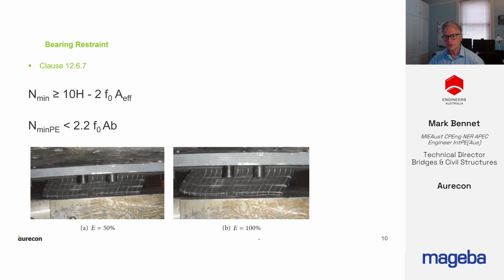When a bearing is subject to shear deflection, the bottom rear corner of the elastomeric bearing curls up. Then with thermal cyclic loading, a caterpillar type action can occur in the cover layer of the bearing that results in the bearing walking out of position. To prevent this, a minimum clamping force needs to be applied to the bearing. To prevent walking, a clamping pressure of 2.2 MPa needs to be applied to the bonded area of the bearing. If the clamping force is not available, then mechanical restraints need to be provided at the top and bottom faces of the bearing.